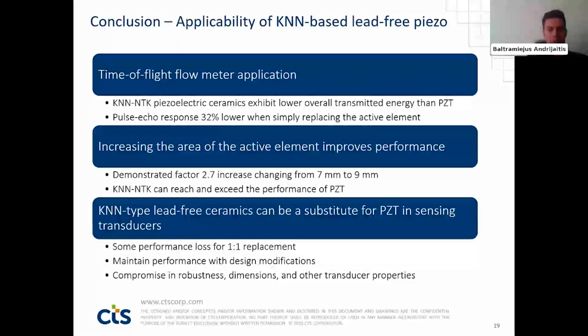To wrap up, KNN NTK LFP0401 ceramics showed overall lower performance compared to our lead-based NC51 material, with a pulse echo response 30%, 32% lower when simply replacing the active element.